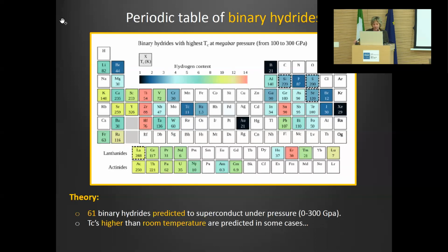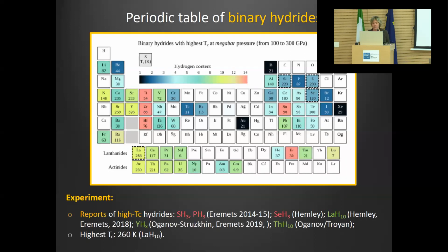You see that there are a few cases here, yttrium, lanthanum, etc., where the predicted TC exceeds 0 degrees Celsius or exceeds even room temperature. And if we look at experiments, as I said before, experiments in this case are complicated. They require a lot of care. There are, of course, many fewer binary hydrides which have been reported to be superconducting. There are a few examples here. And you essentially see that you have red and green high TC superconductors.